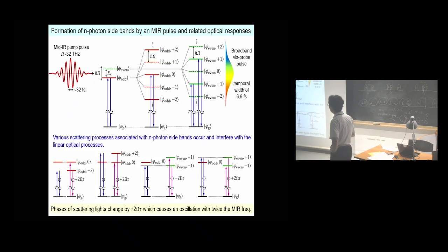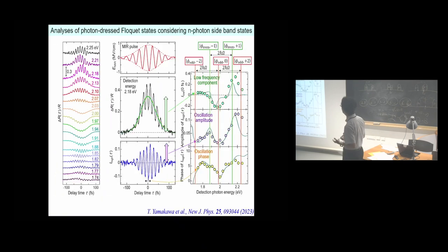At the same time, various scattering processes associated with n-photon sidebands occur, as shown by the purple lines, and interfere with the linear optical responses shown by the blue lines. In this case, the phases of the scattered light change by plus or minus 2 omega tau, where tau is the delay time of the probe pulse. This causes an oscillation with twice the mid-IR frequency. Considering this scheme and assuming the n-photon sidebands as shown by the vertical lines, these three spectra are almost reproduced as shown by the solid lines. This demonstrates that the photon-dressed Floquet state is formed in this compound.